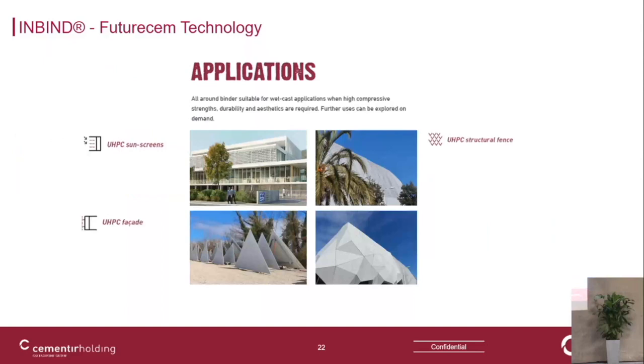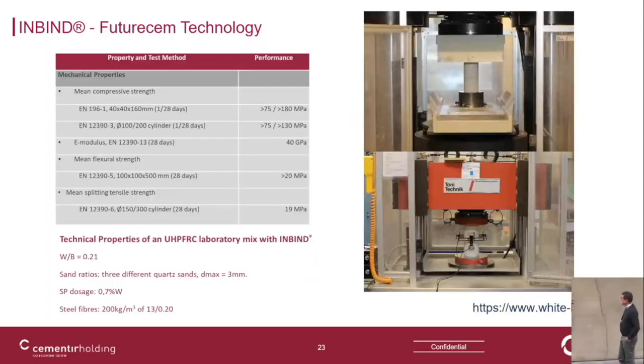InBind can be used for wet-cast applications where compressive strength and durability are required: UHPC sunscreens, facades, structural fences, outdoor furniture and more applications. In terms of mechanical properties, we were able to achieve a mean compressive strength of 130 MPa by cylinder, and the flexural strength is 20 MPa. The mix has a water binder ratio of 0.21, a 3 sand ratio and 200 kilos of steel fiber.